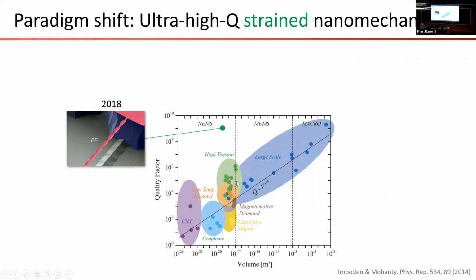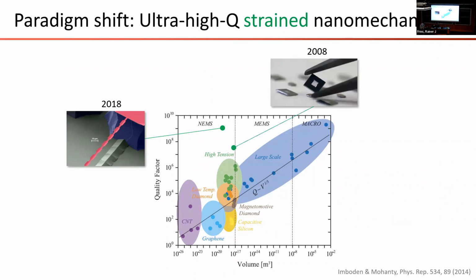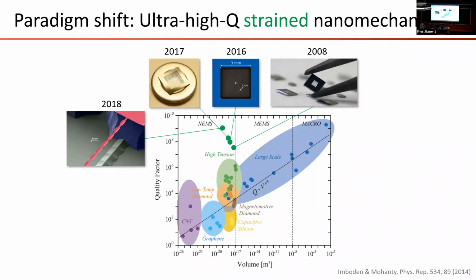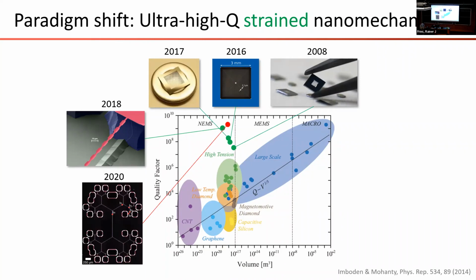These correspond to thin film materials under high tensile stress. And it's really been understanding what's going on here that has given rise in the last decade or so to roughly an order of magnitude increase every 3 years in the quality factor of a nanomechanical resonator, using two techniques in particular. One, making really large objects, and two, patterning them to make localized modes. Most recently, people have been able to get really high stress materials, localize them, and achieve quality factors of 10 to the 10 at cryogenic temperatures with crystalline thin film materials.